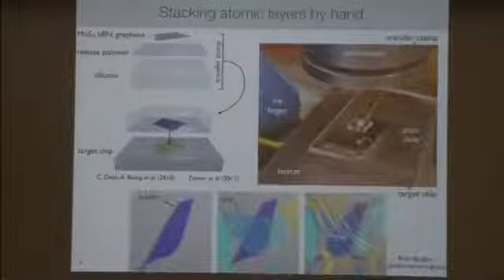And so now I'd like to talk a little bit about how we fabricate devices using these materials. So the starting point is this Scotch tape exfoliation technique that was made famous by graphene, in which single layers of graphene can be deposited on a silicon target chip. And then using the same trick, a second layer that's going to form the second layer of this heterostructure is applied also by Scotch tape onto a transfer stamp that's composed of a piece of silicone and a polymer that, when it's heated up, will release from the silicone.